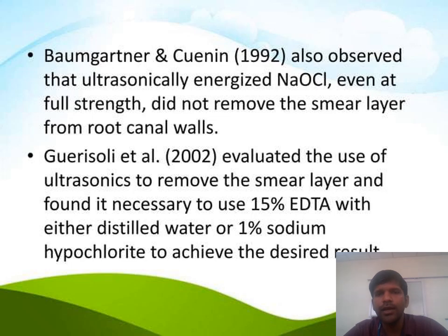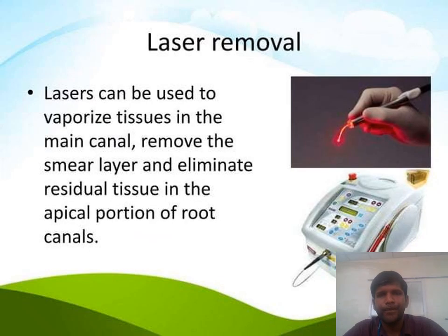Baumgartner and Cuenin in the year 1992 observed that ultrasonically energized sodium hypochlorite, even at full strength, did not remove the smear layer from the root canal walls. Guerisoli et al. in the year 2002 evaluated the use of ultrasonics to remove the smear layer and found it necessary to use 15% EDTA with either distilled water or 1% sodium hypochlorite to achieve the desired result.